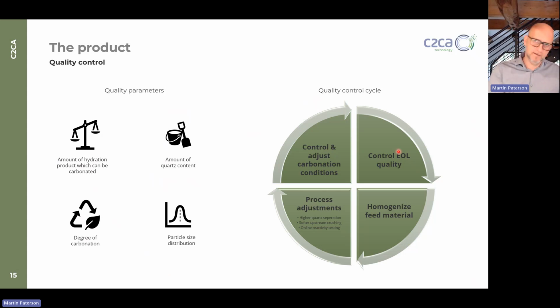So we have a defined quality control life cycle. We first of all check what comes in. The raw material we get, we already try to source high quality raw material in order to have the highest potential, and we can do this. Then we homogenize the feedstock material. If we see that there are high fluctuations in incoming feedstock, we can homogenize already before going into the process. Then we have a permanent measurement of the quality within the process. We can adjust the process parameters in each and every step of our process. And finally, we can test what comes out and can easily adjust the carbonation conditions in order to improve. And if that doesn't work, if there are still too many fluctuations afterwards, we can still blend different qualities in order to make sure that we get a stable quality which can be sold to our customers afterwards.